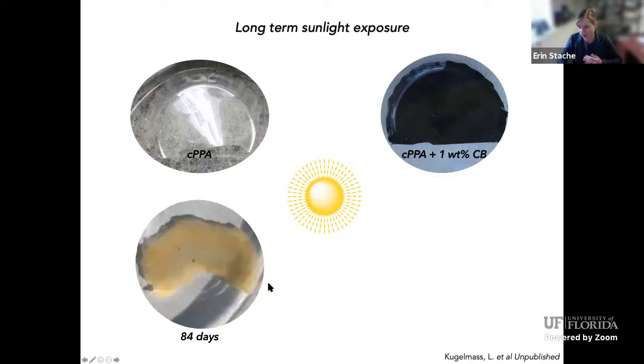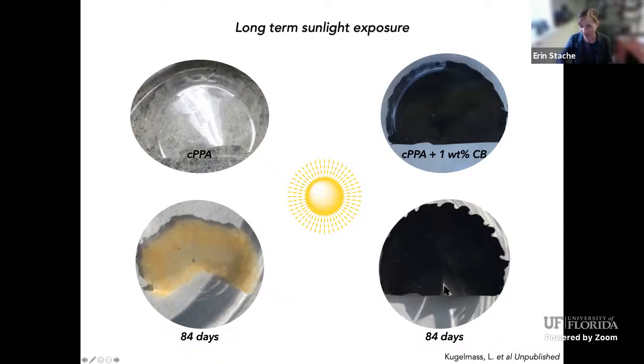And then after 84 days, almost 3 months, it looks really disgusting actually. It doesn't really look like a film anymore. It's turned yellow and it's kind of gooey. It's just not a polymer. After 84 days with carbon black, it seems like it's slightly more brittle. We still need to get a number on those physical properties, but the film itself is still intact.